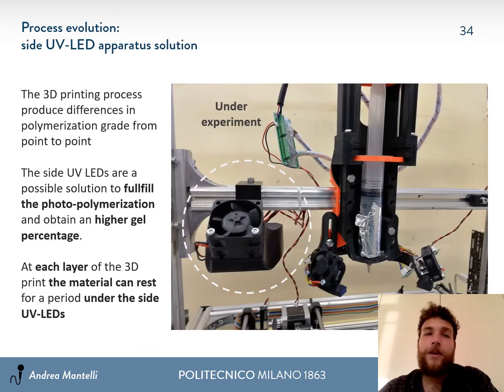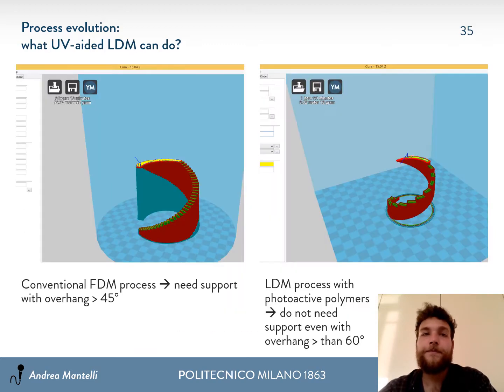But we have seen that during 3D printing the photopolymerization of the material is not completed, and so we need a UV post-curing. In order to overcome this problem, we are now testing a side UV LED apparatus, where after each layer the object can rest under it for some seconds and complete the photopolymerization.